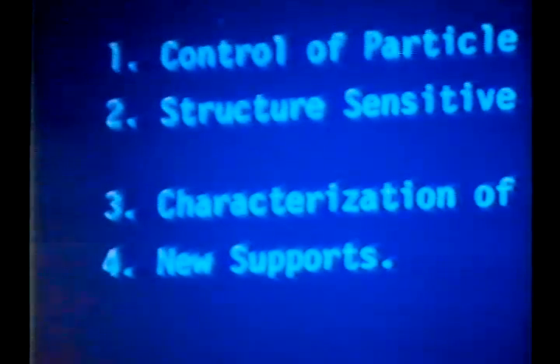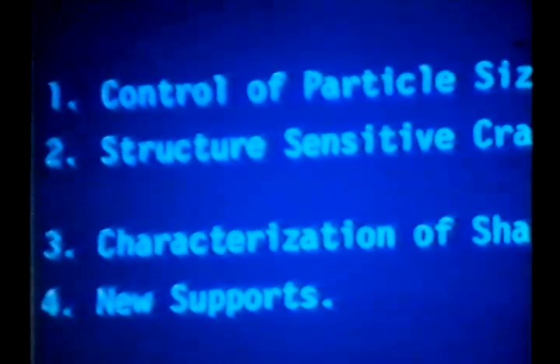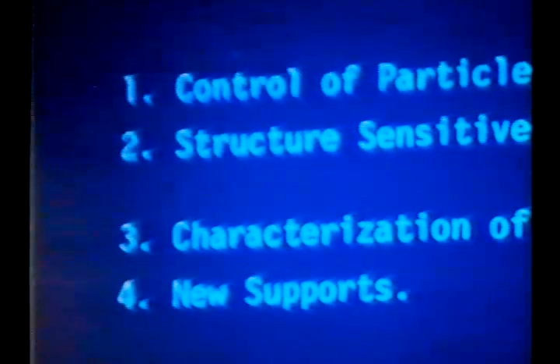At 10 watts, you grow the particle. We thought, well, gee, great. Zoom in on the power: 3 watts, we'll get so many angstroms, 5 watts, we'll get this, and 10 watts, we'll get this. Well, it doesn't work that way. It seems like it's an on and off type thing. There's like a threshold. At 3 you get small, and 5 you get small, but around 10 or so, the particles start to sinter and aggregate, and they just get right out of the zeolite. They move out of the zeolite. So we don't have a lot of control over that.